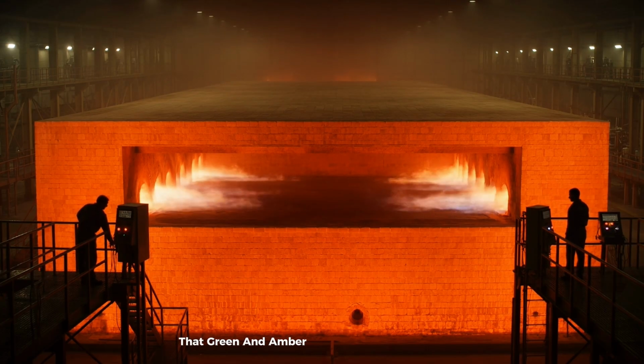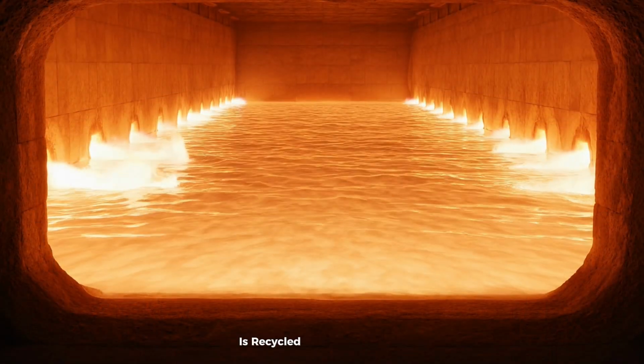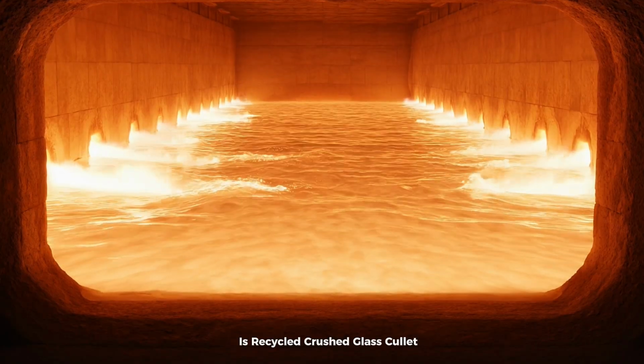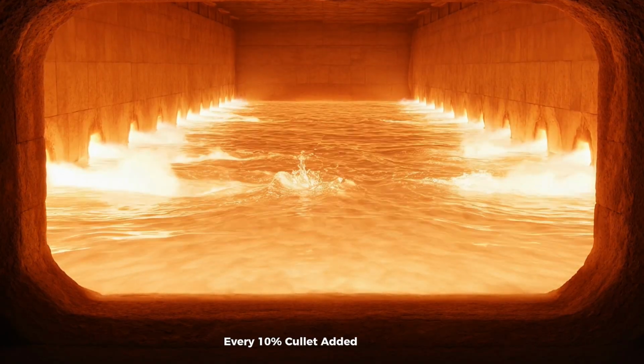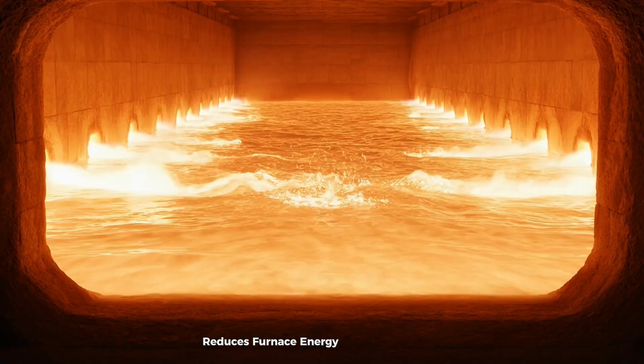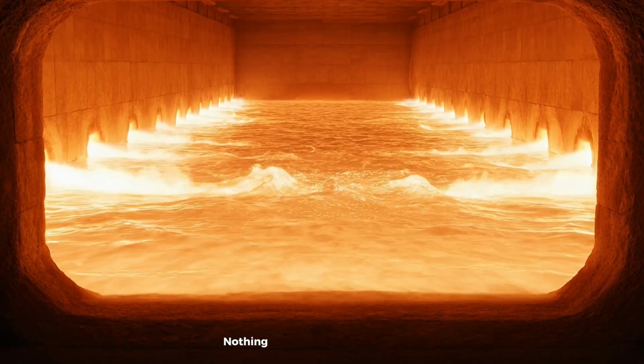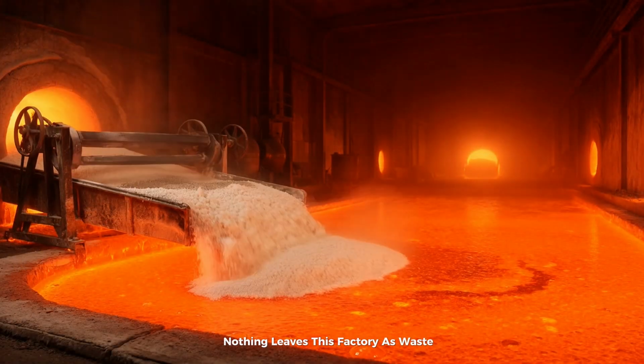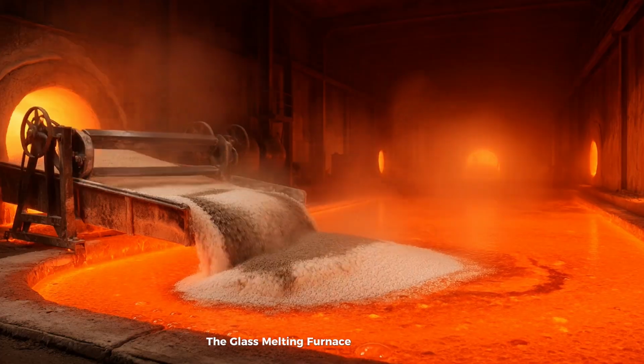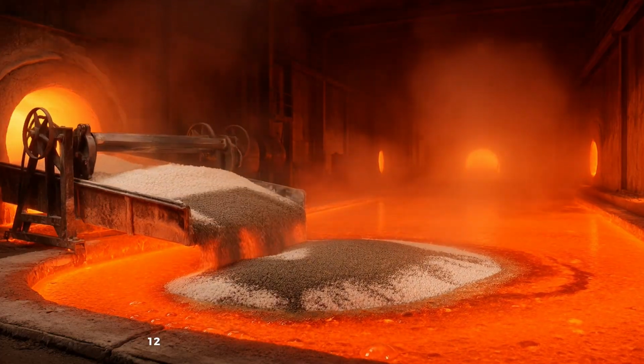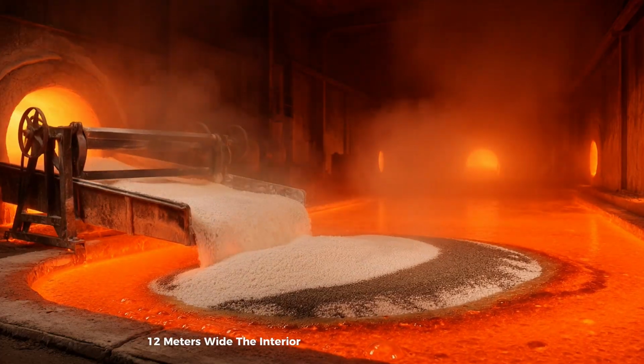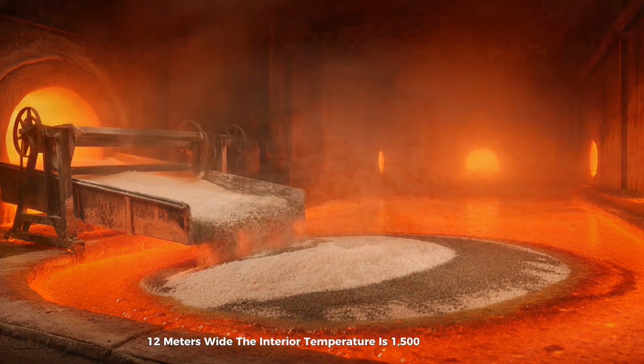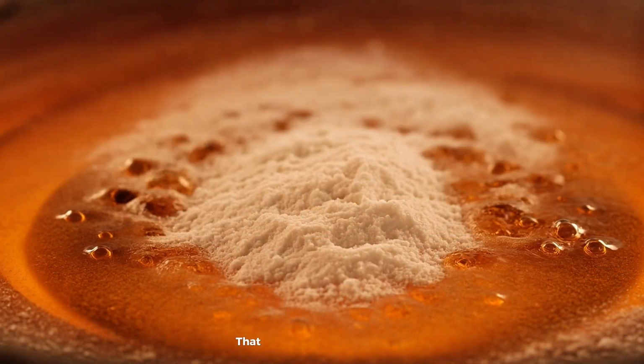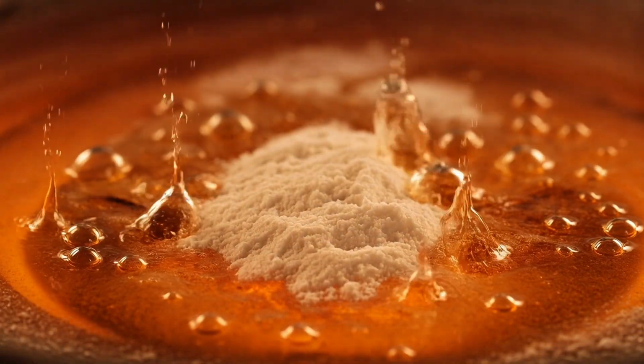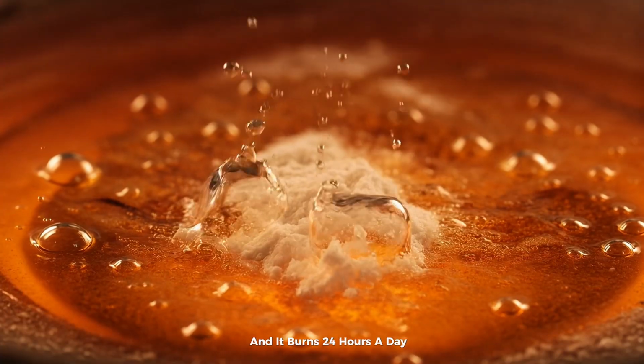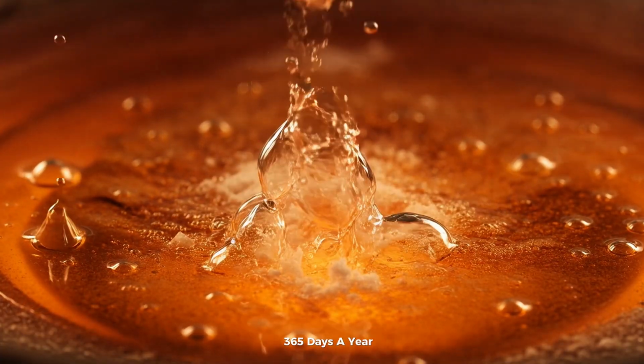That green and amber material falling into the mixer is recycled crushed glass, cullet. Every 10% cullet added to the batch reduces furnace energy consumption by 4%. Nothing leaves this factory as waste. The glass melting furnace is 30 meters long, 12 meters wide. The interior temperature is 1,500 degrees Celsius. That is hotter than volcanic lava. And it burns 24 hours a day, 365 days a year.